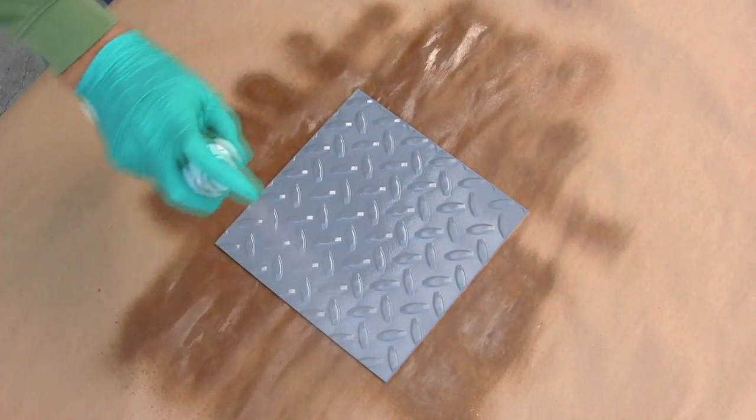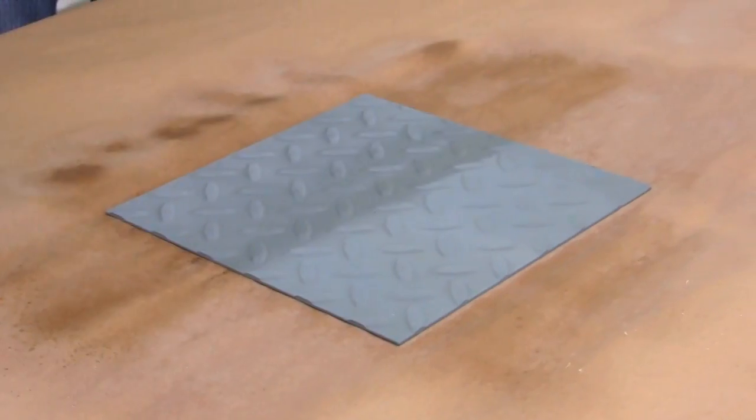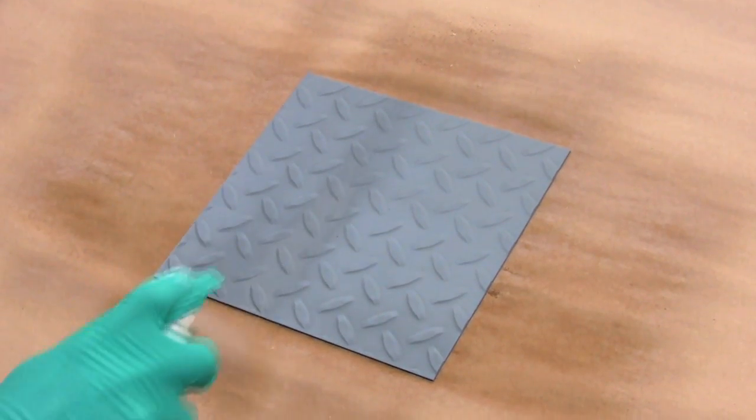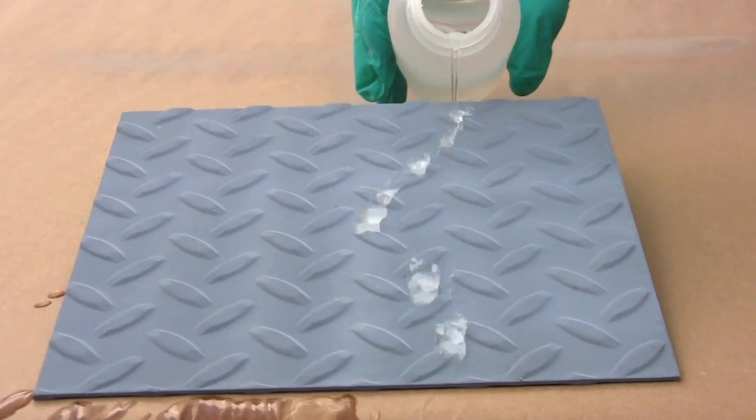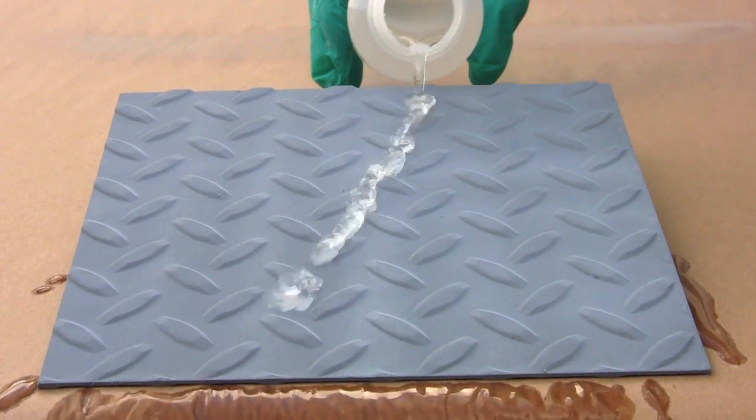After 15 to 20 minutes of dry time, you will be ready for the next step. Apply the top coat using the same method and guidelines described for the bottom coat. We recommend using a separate sprayer for the top coat. As the top coat dries, it will become hazy in appearance. The Ultra Everdry coating will become super hydrophobic within 30 minutes of the top coat application.